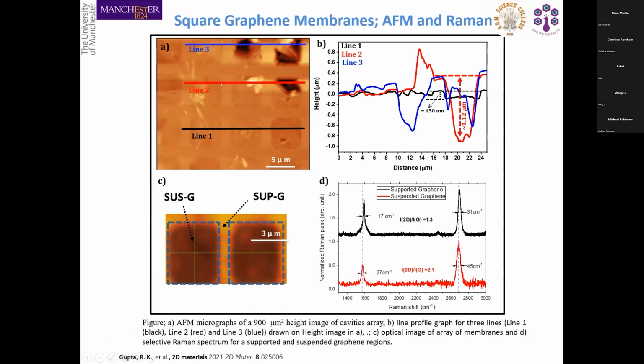And the AFM image also tells us that the cavity depth is around 1 micron, and when graphene goes on top of it, it sags around 150 nanometers. So it's a pretty flat membrane. With Raman spectroscopy, you can identify the points where the graphene is suspended and where the graphene is supported.